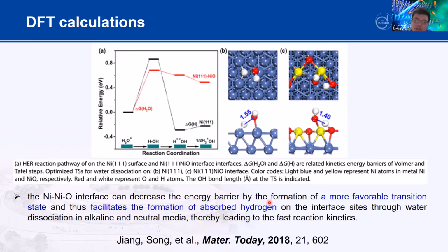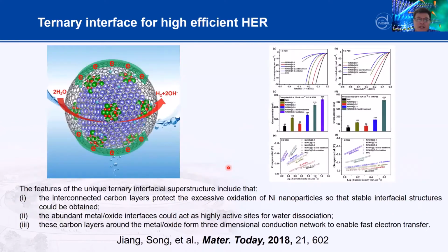That means you can use these materials as a catalyst for electrocatalytic water splitting. So this is what we understand: how to identify the ternary interface and understand how this works for the hydrogen evolution reaction. So this is the performance. Since this is the XAS club, I do not want to show too much about the results. Just want to show that by XAS, we can identify the interface between the metal oxide and the carbon.